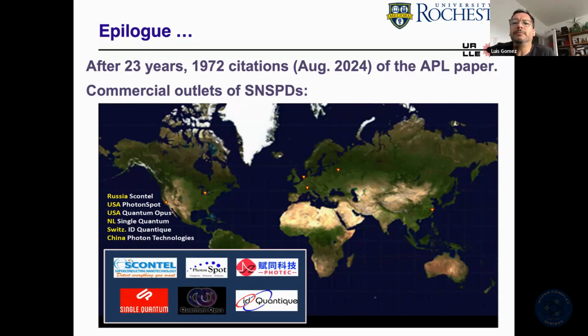Okay, so you need to have large photon energy, at least on the order of half an electron volt, to make a measurable signal. In the simplest way, the gain in the detector is the ratio between the energy of your photon and the energy gap, or coupling of Cooper pairs. So if I have 2 eV and 2 milli-electron volts, I have a gain of 1,000.